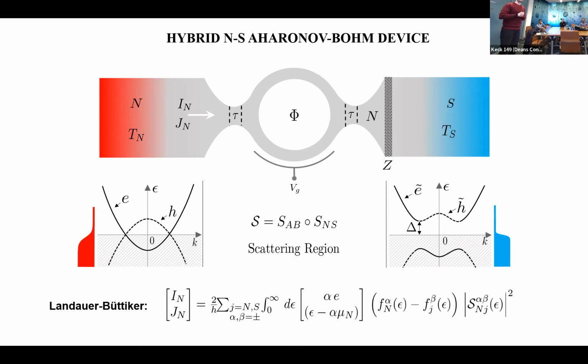The middle part of the system corresponds to the scattering region, where electrons and holes scatter inside the system, and this region is characterized by its scattering matrix, calligraphic S, that we obtained by combining the scattering matrix of the Aharonov-Bohm ring, S_AB, and the scattering matrix of the interface with the superconducting lead, S_NS, which is the one that takes into account the Andreev reflection processes. So these are processes that convert electrons into holes and vice versa.